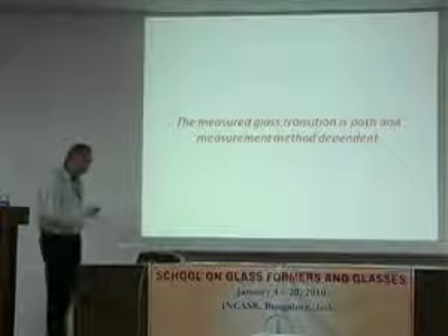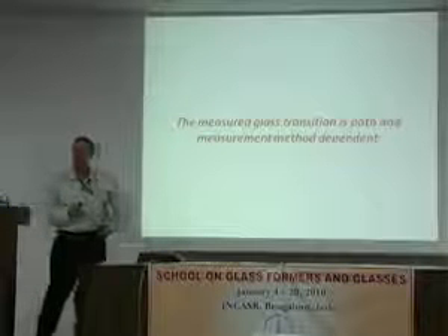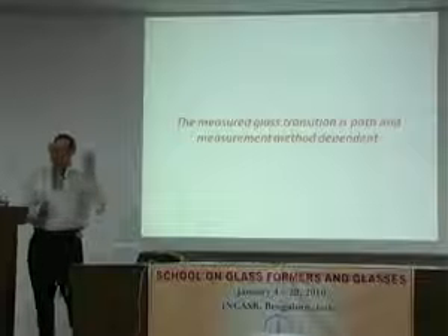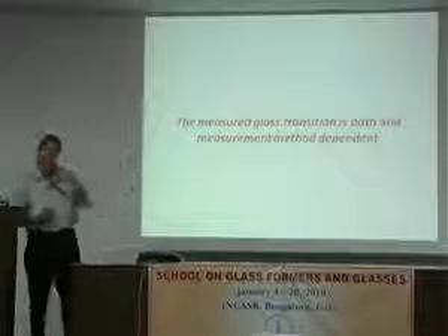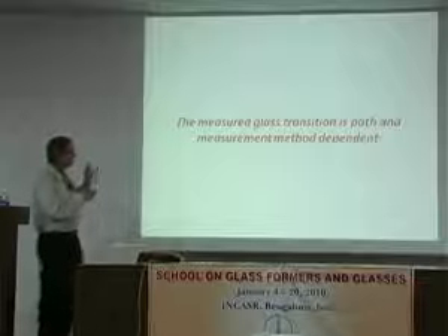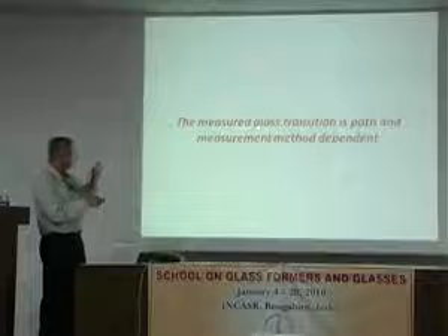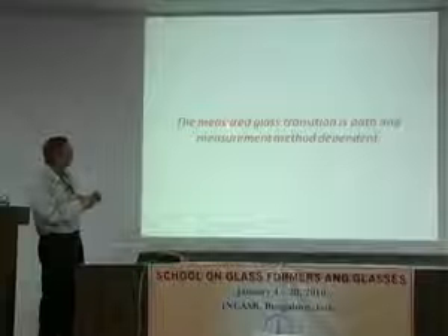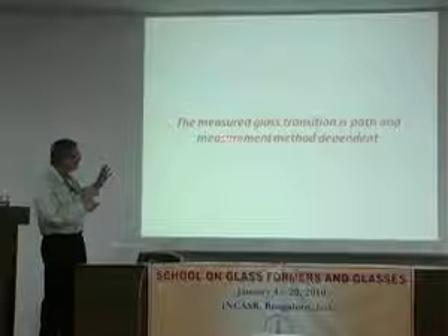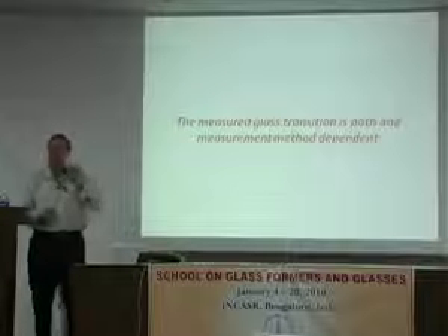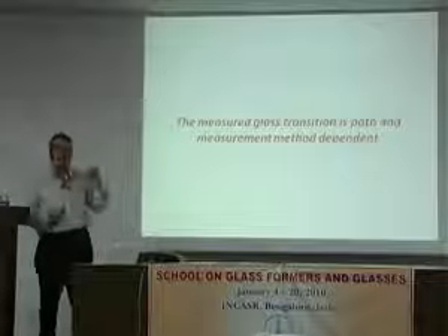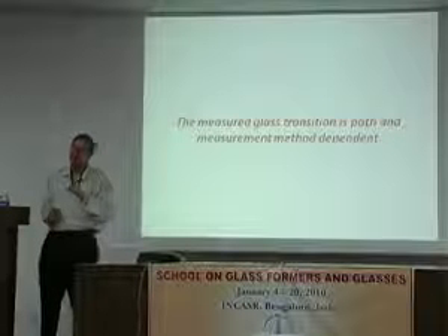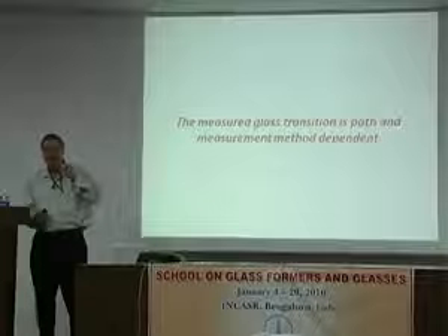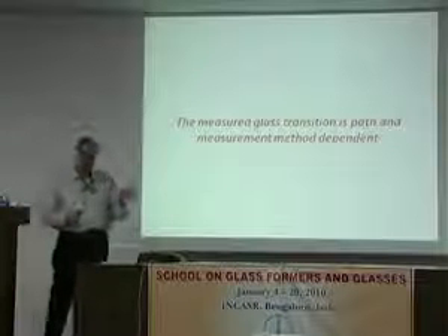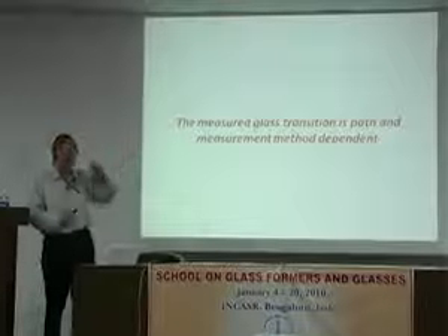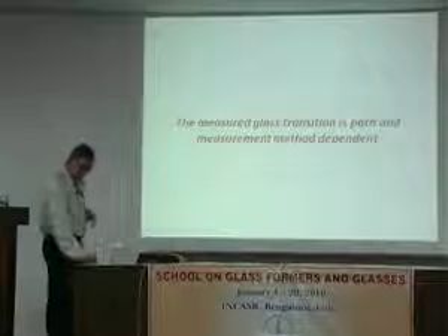So I like to make a point of the fact that we've been talking about the glass transition quite often, although the last talk did not make it a point. But the glass transition temperature is not a temperature. It's something that's path and measurement method dependent. So depending on exactly what you do, the actual value you report for the glass transition temperature is going to be different. So part of this is because of the kinetics. Part of it is perhaps because of the path dependence itself. So that's something we have to be concerned about.